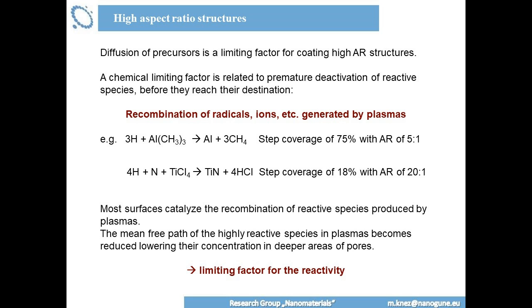If you have a very, very high aspect ratio and extremely energetically active radical species, they will recombine. They will not reach the pore. So it is always tricky, and I think Erwin Kessels is not here to complain about it, and it's not something negative. But what I mean is, if you operate with plasmas, it is way more tricky to have high aspect ratios conformally coated than if you work with thermal ALD. But even in thermal ALD, you will have problems if you really go to aspect ratios beyond 1 to 10,000 or whatever.